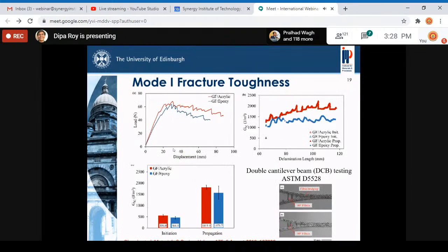Now, we also investigated the interlaminar fracture toughness of both composites, acrylic and epoxy. We followed ASTM D5528. This is a double cantilever beam test, and this is how the samples look. By doing this test, the initiation toughness of the acrylic was marginally higher than epoxy, and the propagation toughness was significantly higher than the epoxy.